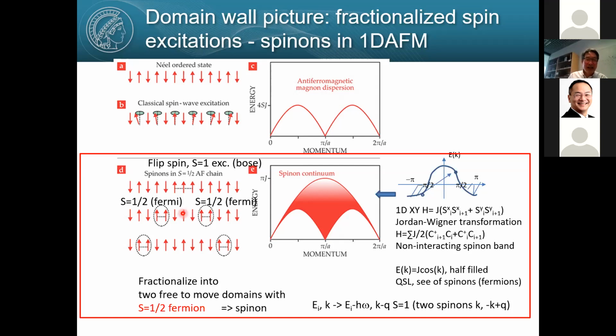And this we call fractionalized spin-wave excitation. Those domain boundaries, you notice, carry a spin 1/2 degree of freedom, and they behave like fermions. So in a one-dimensional anti-ferromagnet, the spin-wave excitation fractionalizes into two freely moving domains with spin 1/2, fermions. This spin 1/2 degree of freedom is often called a spinon. This exotic excitation called a spinon behaves very differently from a magnon. If you measure the excitation spectrum, you do see a continuum of excitation, rather than a line of excitation.